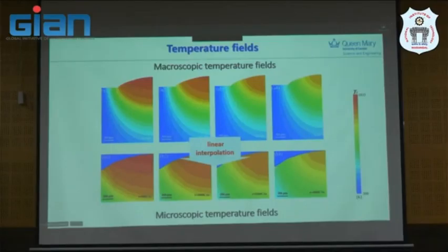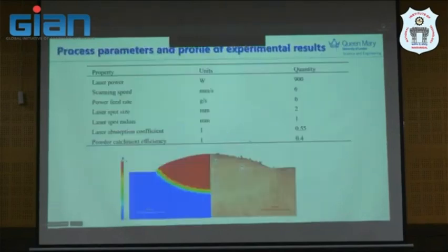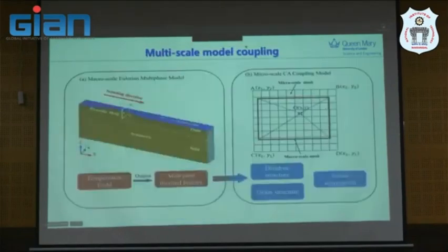So this is another numerical treatment, where we need to interpolate the temperature in between. Let's say your mesh is 1 millimeter and you want 1 micron. That means you need to interpolate the temperature in between. Yeah, that's what it's doing. Thank you.